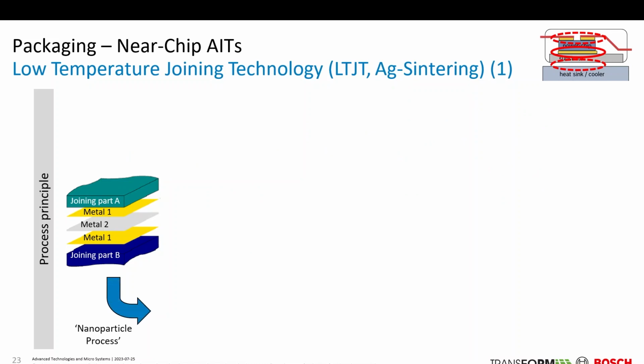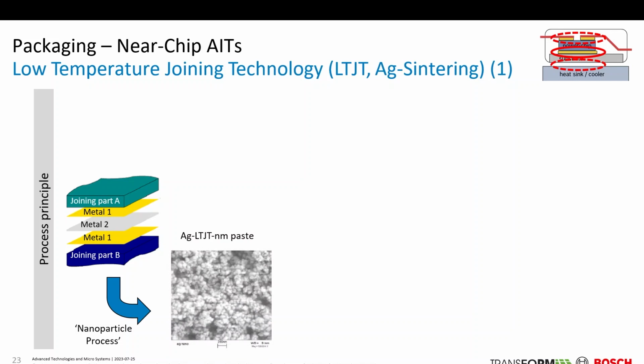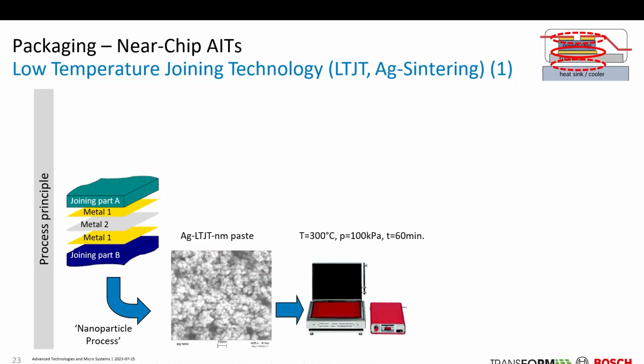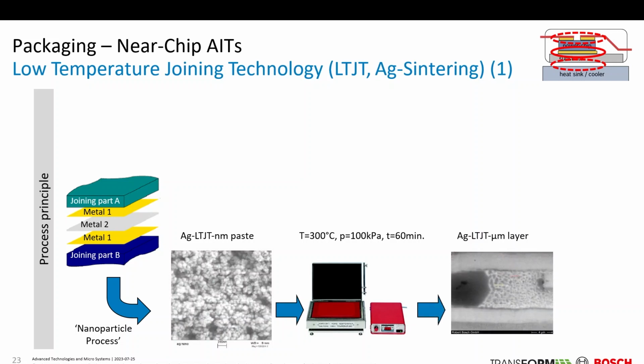An alternative is a nanoparticle process you can apply. Then we have particles on a sub-micrometer scale or even a nanometer scale. They are more or less spherical, and not of the flake type. Okay, the process parameters are reduced on the pressure scale, so it's below the megapascal range. But you need a little bit more time, and as well you get a silver sintered layer between your semiconductor part and your circuit carrier, as one example you can join.